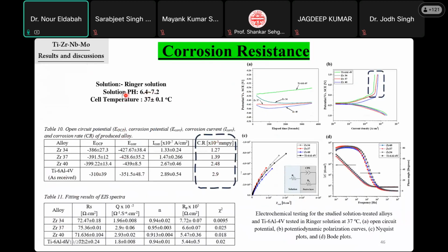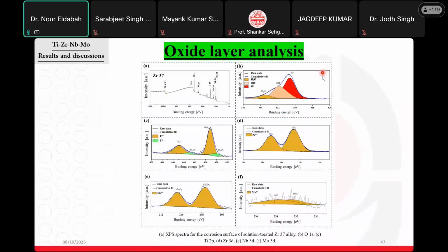Actually, you should accomplish your test in a solution that imitates the human body fluid, like phosphate buffer saline or Ringer solution, to be injected inside the human body in case of dehydration. Also, you should stabilize the cell temperature around 37 degrees Celsius to simulate the implantation environment. Also, the oxide layer you should analyze using XPS. The oxide layer consists of titanium oxide and zirconium, niobium, and molybdenum oxides, all biocompatible, after fitting the XPS spectrum.